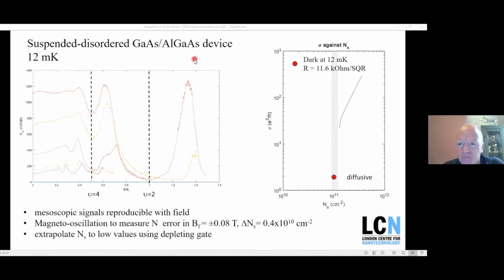This is what happens at slightly lower temperatures now. This is a disordered gallium arsenide device. This is at 12 millikelvin. This is cooling the device down to low temperatures. And what I've had to do is just illuminate the device, to use a persistent photoconductivity effect to put carriers in there. These were the first devices that weren't gated, so we couldn't use the gate effect to go down to very low carrier densities.